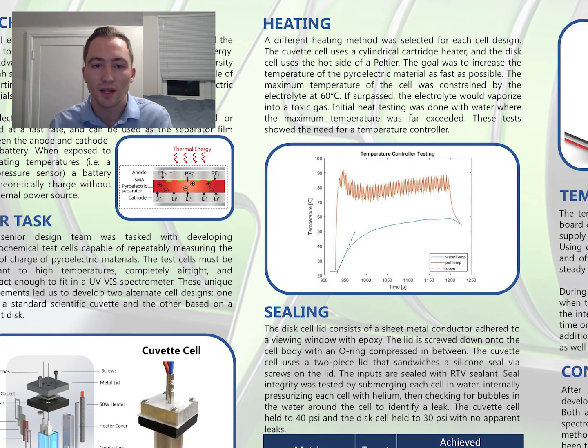Sealing capability was tested by filling a cell with helium gas until leakage occurred. Both of the cells performed well, with the disk cell obtaining a pressure of 30 psi and the cuvette cell obtaining a pressure of 40 psi.